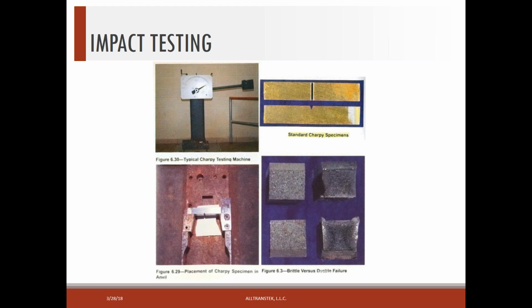And of course, the more foot-pounds that we have during a break test like that, then the more impact resistance we have. And in the upper right-hand corner, you see the typical Charpy specimen, and usually it's a little bit over 3/8 of an inch square. The typical dimension is 0.394 by 0.394, and then the notch itself, which is seen in the upper view, is machined to very precise specifications also. That's the notch initiation point for the fracture of a Charpy specimen, and then we'll measure the foot-pounds and see how much energy is required to break it.